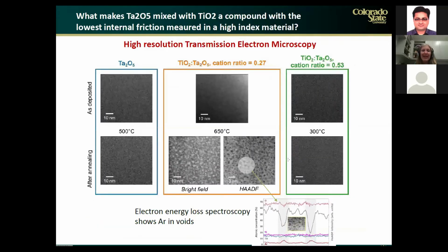When we look at the material at the nanoscale, and we did that by using images from transmission electron microscopy, shown here, we compare just plain tantalum pentoxide with the tantalum pentoxide mixed with titania with a cation ratio of 0.27, and the alloy with a higher cation ratio. And what we see is that at 650 degrees C, which is just 50 degrees C below the temperature at which we show clear signs of crystallization, the material consists of grains or crystallites that are very small, nanometer size, mixed with some dark spots that you can see here better,